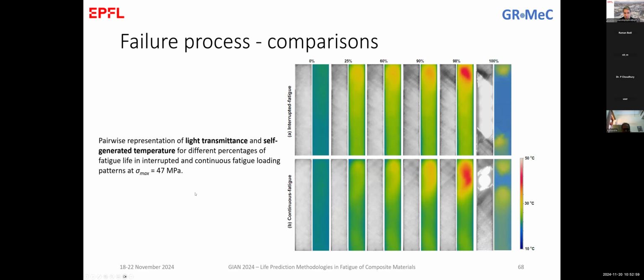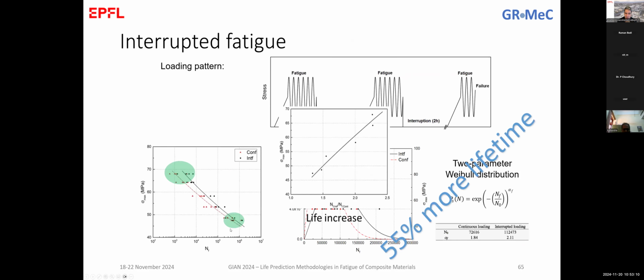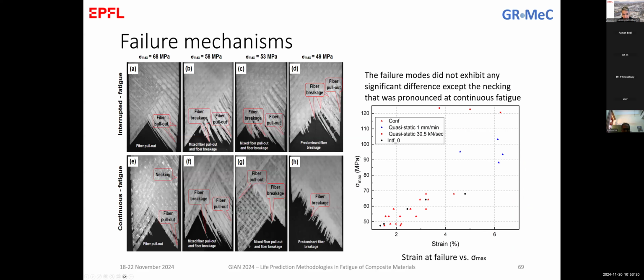And as we said before, when we are at lower stress levels, we have similar behavior of interrupted fatigue and continuous fatigue. And this is the reason that if you go back to the SN curves, at low stress levels, we see that the difference is not so significant between the two loading patterns. The same behavior for the failure mechanisms. At high stress levels, we have mainly fiber pull-out, and at lower stress levels, we have fiber pull-out and fiber breakage. What is also different between the two is that in the interrupted fatigue, we do not observe this significant necking that we observed in the continuous fatigue at high stress levels.